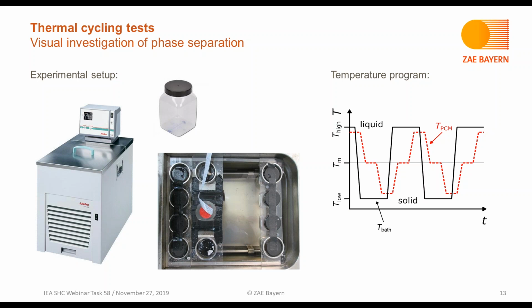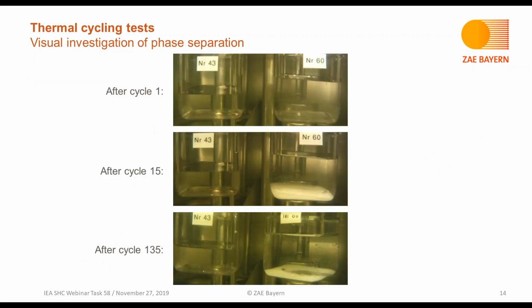What we found out, which is very important and also very useful, is to have a visual investigation of phase separation. Therefore, we measure the eutectics in such transparent bottles, put them in a thermostatic bath, and then take pictures during the thermal cycles. And this is shown on this slide.